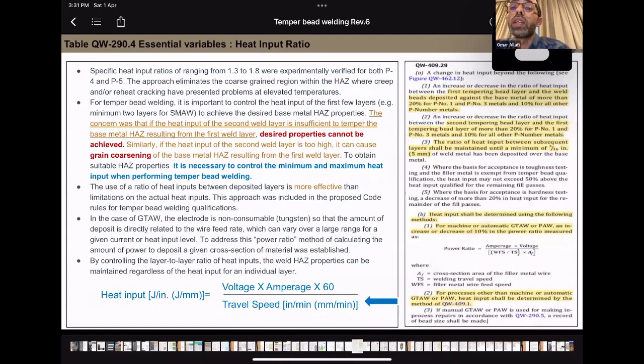So the concern was that when you have a heat input of the second layer that is insufficient to temper the base metal, the desired properties cannot be achieved. And if the heat input of the second layer is too high, it can cause grain coarsening, as we saw previously in the photos. So it is necessary to control the minimum and maximum heat input when performing temper bead welding. This is why heat input ratio was developed.